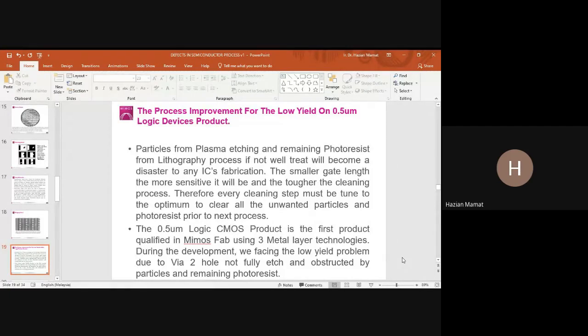The particles from the plasma etching and remaining photoresist from the lithography process, if not well treated, become a disaster to IC fabrication. The smaller the gate length, the more sensitive it will be and the tougher the cleaning process. Therefore, every cleaning step must be tuned to the optimum to clear all the unwanted particles and photoresist prior to the next process. The 0.5 micron logic CMOS product is the first product qualified in CMOS Fab 2, which is on the 200 mm wafer foundry.